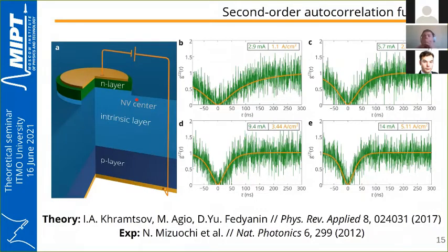Next, we decided to test the obtained theoretical approach in practice and reproduce the recent experimental results on the measurements of the G2 function and electrical pumping. At that time, there were two works, and only one contained all needed parameters of the diode used. The parameters that were not known do not affect the G2 functions. Since the electroluminescence process depends on the electron and hole density in the vicinity of the color center, I performed the stochastic simulation of the electron and hole transport in the PIN diode corresponding to the experimental diode, and using the developed theoretical approach,